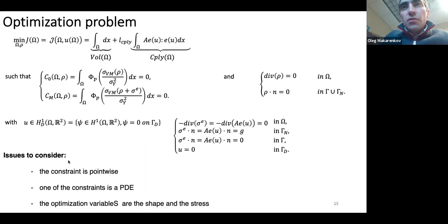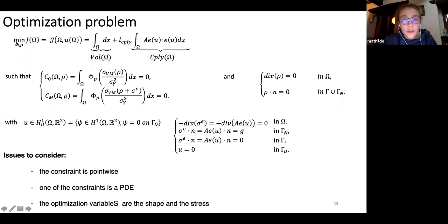So yeah, that makes a new optimization problem in which we now have the shape and a stress. And the stress must satisfy the pointwise constraint, we can deal with it the same way as before. So we now have a constraint that says that the residual stress must remain in the circle at each point, and that the residual stress plus the ideal elastic stress must remain in the circle at each point. Well, we are still minimizing the volume. And this stress must be self-equilibrated, so it means that it has to satisfy this equation.